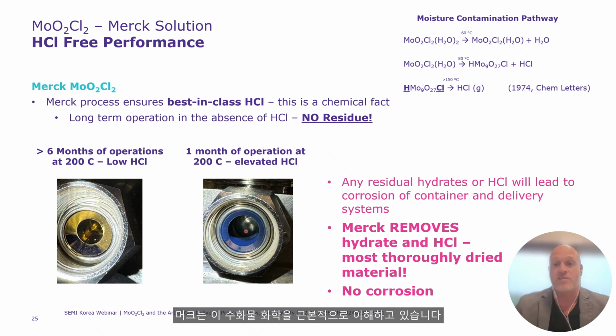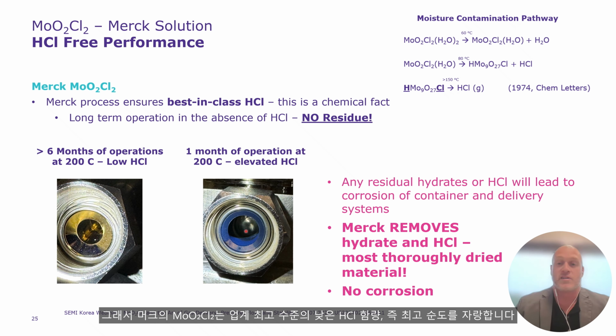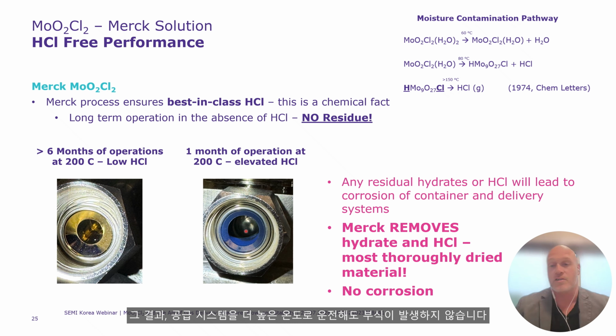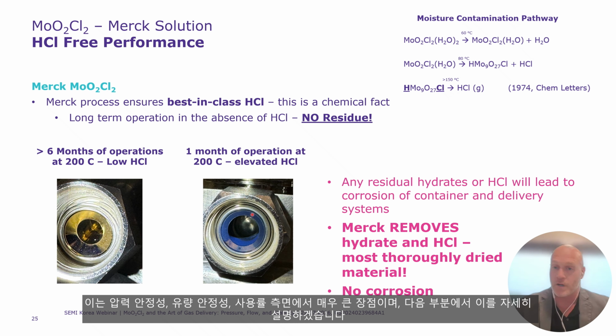And so that's really it: Merck fundamentally understands this hydrate chemistry. We fundamentally understand within our processing how to remove this HCl. And so our material is state-of-the-art in HCl content, highest purity. That means we can drive to higher temperatures in our delivery system and not get corrosion. That's going to be a really big deal for pressure stability, flow stability, and utilization, which we're going to drive into next.